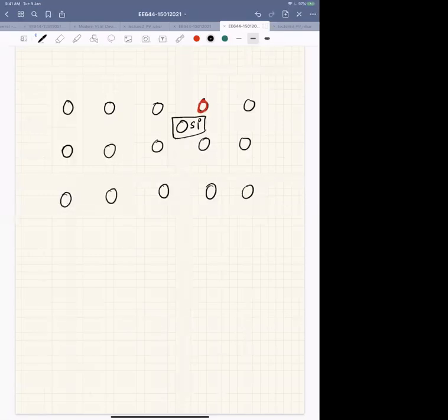So the moment this arsenic replaces silicon there, then arsenic will bond, right? But this silicon, since it is not in the substitutional site, is most likely in an interstitial site, somewhere lying between two atoms, right? And it is not active, right? Active means it is not participating in the bonding process, right? So that silicon atom is still there, but it is not in the lattice site, and since it is not in the lattice site, it will not participate in the bonding.